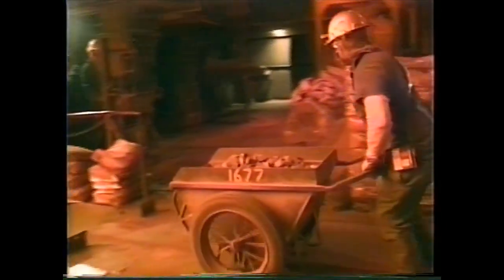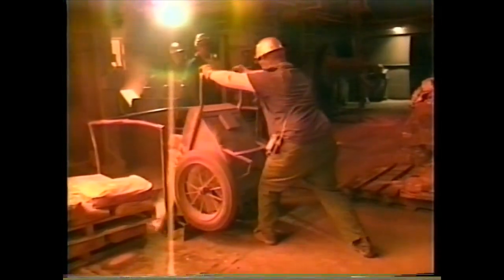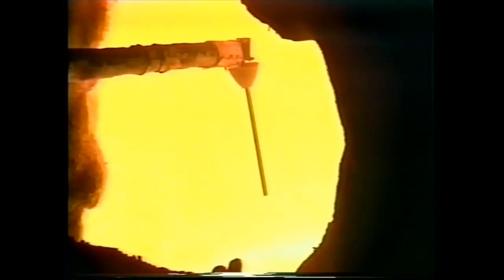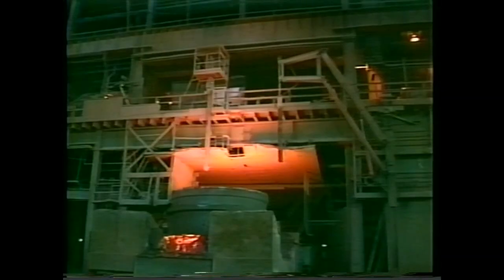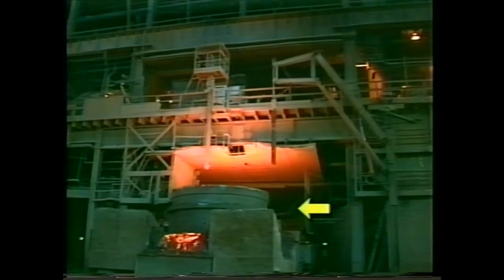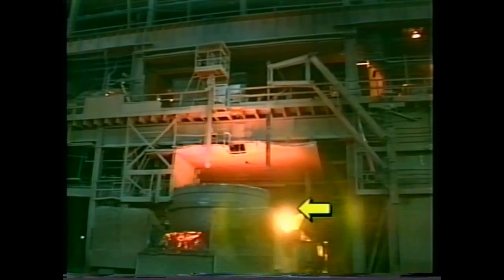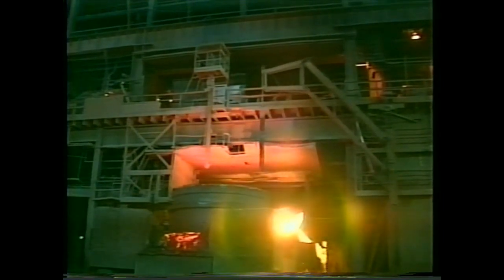As the steel is being tapped, the stocker discharges the alloy additives down the discharge chute into the steel ladle. With approximately 20% of the steel remaining in the vessel, the furnace man drops a slag dart into the vessel's tap hole. The slag dart allows the vessel to be drained of steel while the unwanted slag remains in the vessel. Upon completion of the tap, the furnace man pours the remaining slag into the slag bowl.